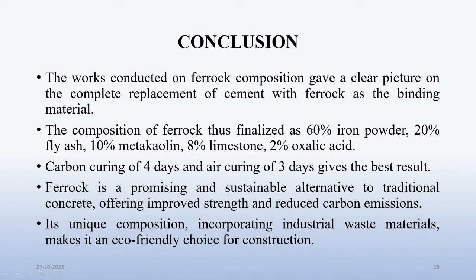In conclusion, research on Ferroc composition shows that a complete replacement of cement with Ferroc as a binding material is achievable. The finalized composition is 60% iron powder, 20% fly ash, 10% metakaolin, 8% limestone, and 2% oxalic acid. Carbon curing of four days and air curing of three days gives the best results. Ferroc is a promising and sustainable alternative to traditional concrete, offering improved strength, reduced carbon emissions, and an eco-friendly composition incorporating industrial waste materials.